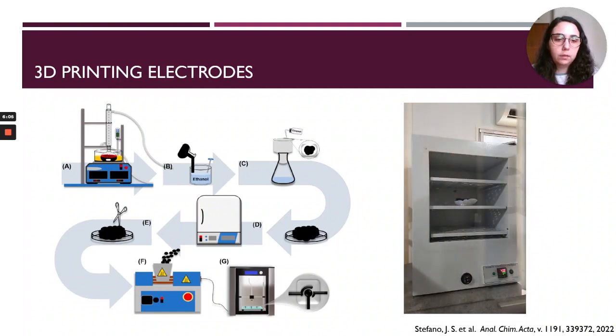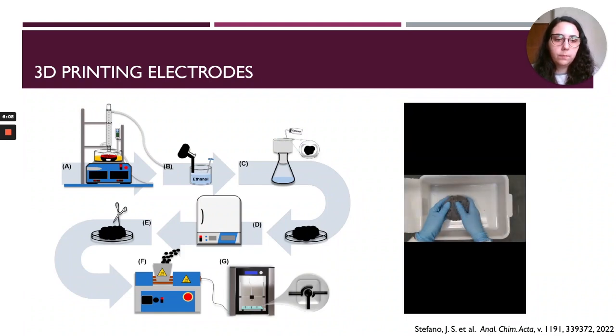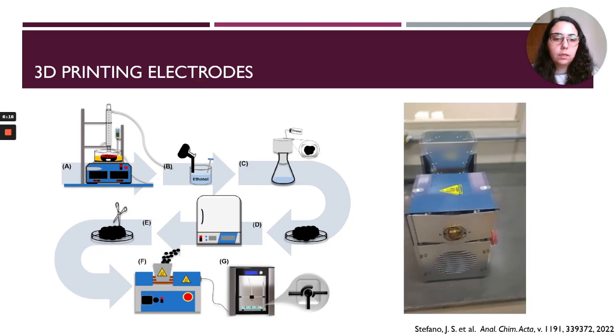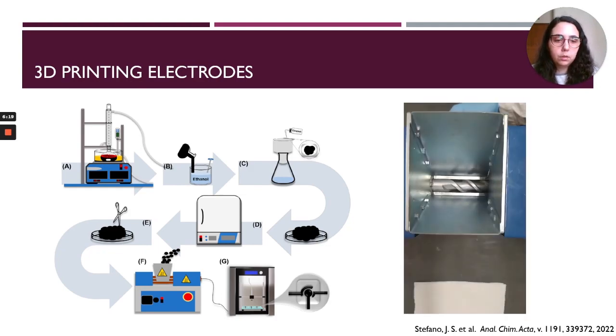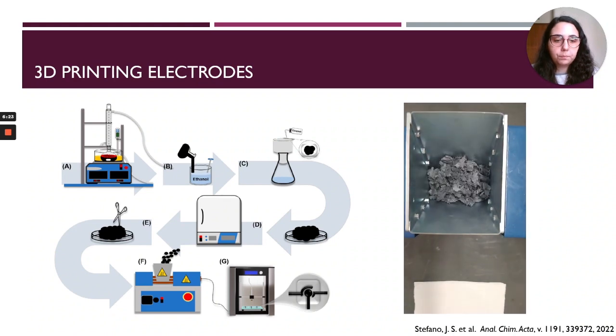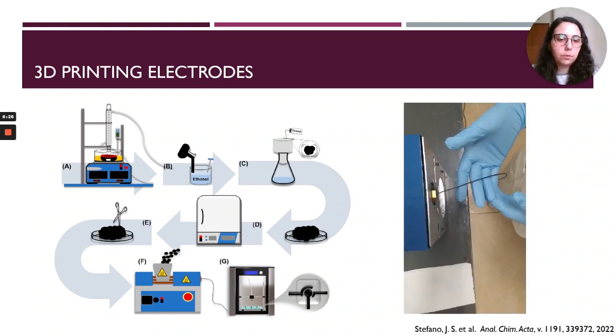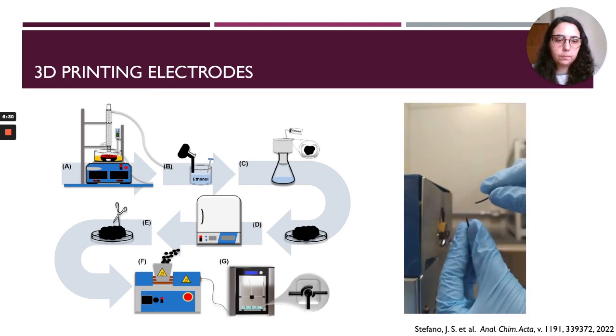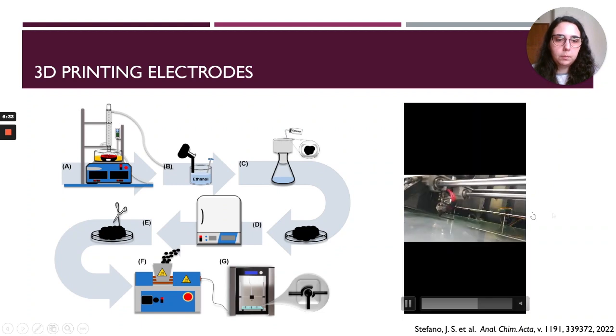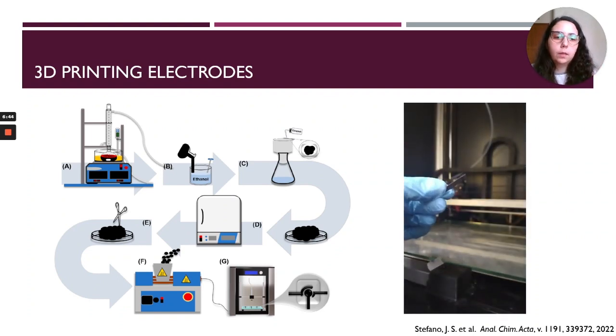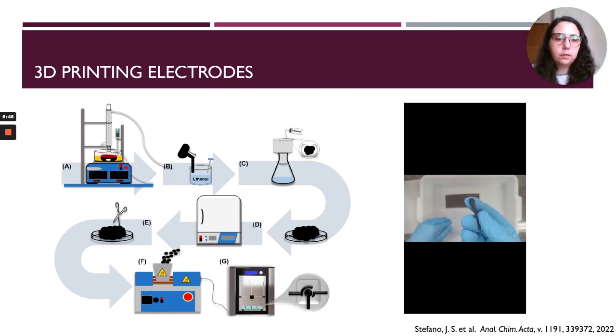And after that, we can dry the composite. After drying, we break it into smaller pieces using scissors and our own hands. And these small pieces can then go to the extruder to produce the filament. So this is the filament that will be used for 3D printing the electrodes. So then the filament is added to the 3D printer, and now we're printing an electrode. After printing, the electrodes get some grooves in them due to the printing process, and then we do some mechanical polishing just to remove these grooves and to make the surface smooth.